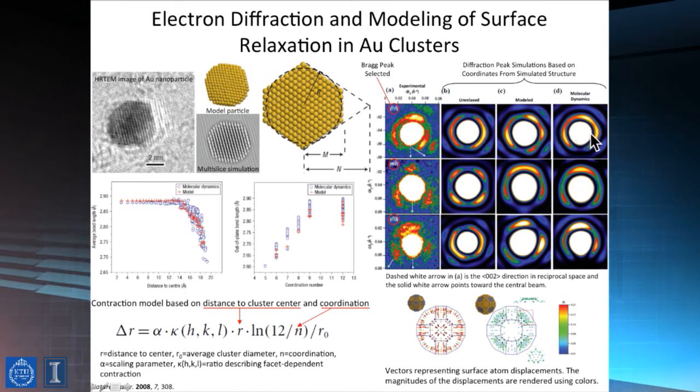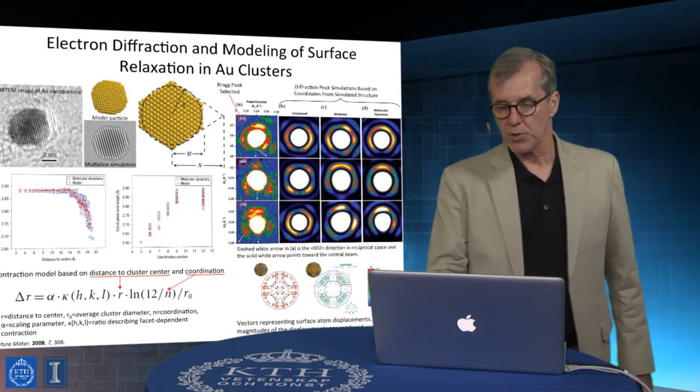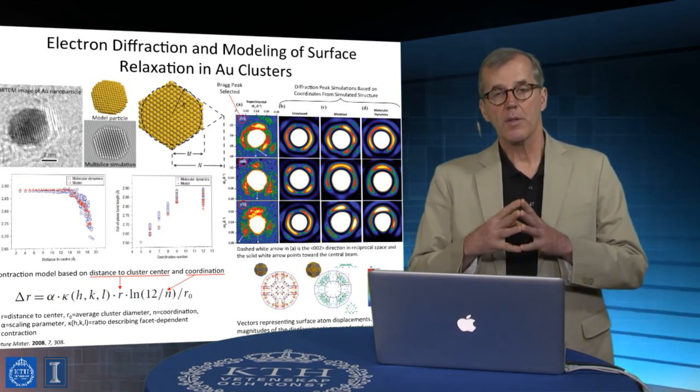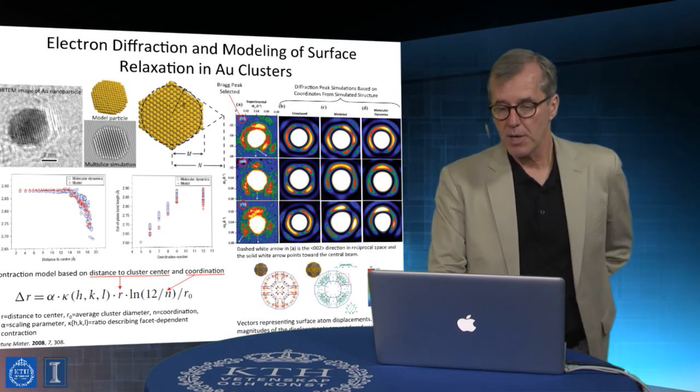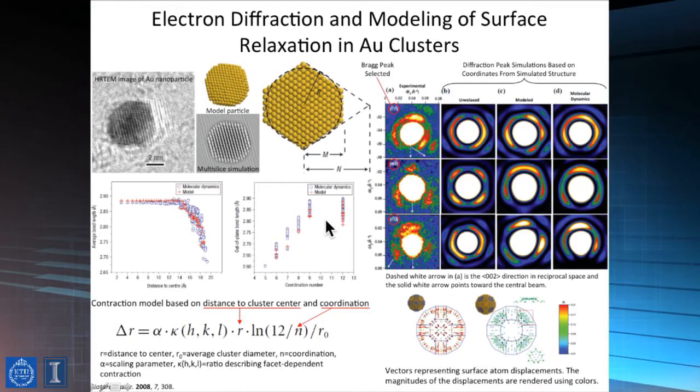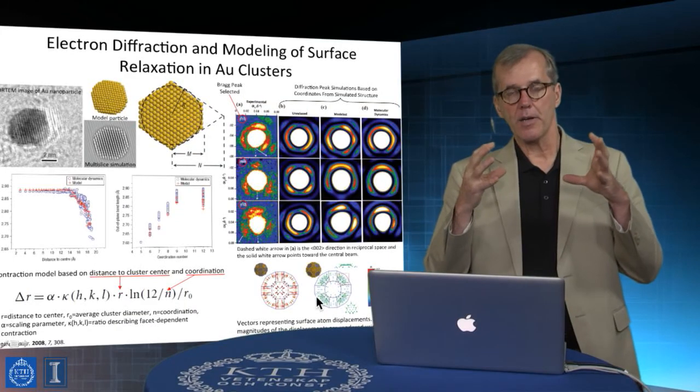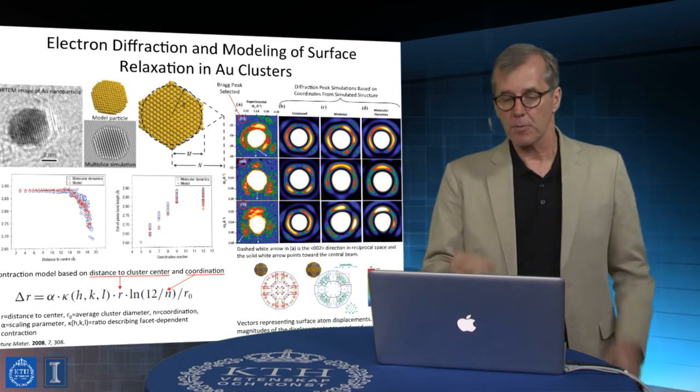And the important point that's actually established here is to not only understand where the atomic positions are, but to understand what kinds of structural complexity are also embedded in the object. Because here what we're going to do is not just look at a two-dimensional projection, but wrap that up in a three-dimensional model of the atomic positions, and also allow the atoms to relax from their theoretical bulk-like bonding positions. And the reason you would do this is because crystals that have finite truncation planes actually have peculiar forms of structure in them.